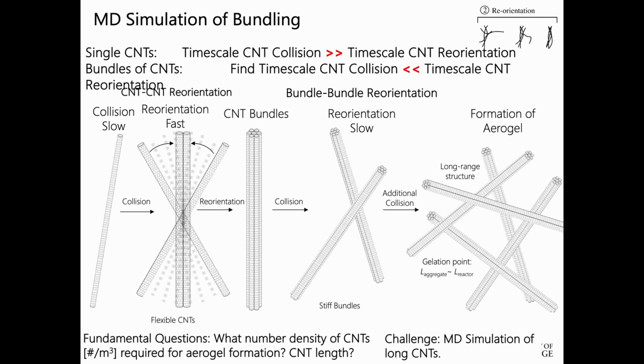And so our emerging understanding of this process is that you get individual nanotubes that collide together. The rate at which they form these bundles, at least initially, is extremely fast relative to their collision rates, even though their collision rates are fast. But what we know is that that must slow, because eventually we get a material out that looks like this, where we get lots of bundles, of say 10 nanotubes roughly in a bundle, forming a macroscopic material.